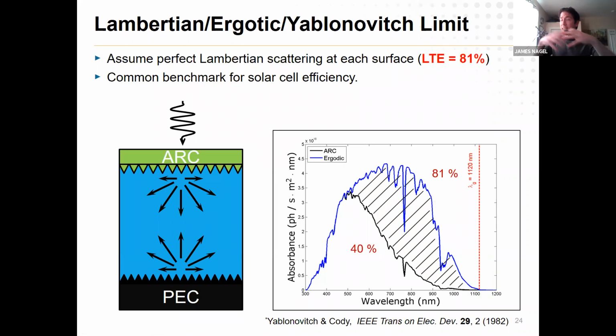And the idealized best you can do, so we'll derive this later, you imagine just perfect Lambertian scattering at both surfaces. And it turns out you can get upwards of about 81% light trapping efficiency for just a 1 micron cell of crystalline silicon, which is pretty good. It's not bad at all. And so you can imagine if I maybe just go to 2 microns or so, I might get up to like 90, 95%, say. So I don't have to get very thick in order to trap essentially nearly 100% of the photons if I am clever with my scattering inside to trap the light.